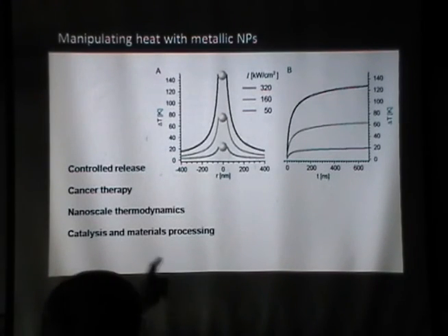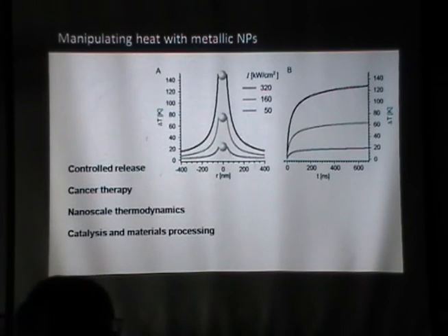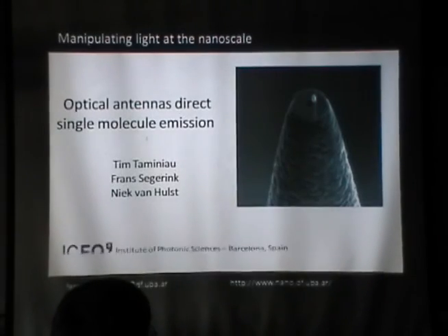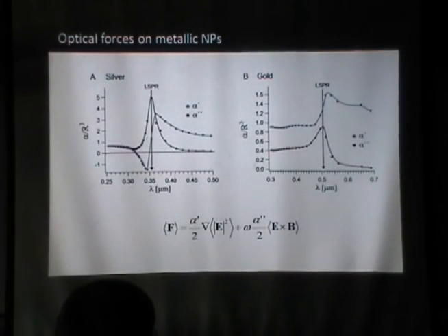I have a question. So the heating effect, is it most efficient only at the wavelengths of surface plasmon resonance, or can you get strong enough heating also if you are substantially away from that wavelength? It's given by the absorption cross-section. In general, the answer would be that the plasmon resonance is the maximum, and you should aim at that. Like in silver, you see you have almost no absorption if you go too far away. In gold, you still have some absorption, which is not due to the plasmon resonance. If you go further, the metal becomes transparent, absorbs no light, and there's no heating.